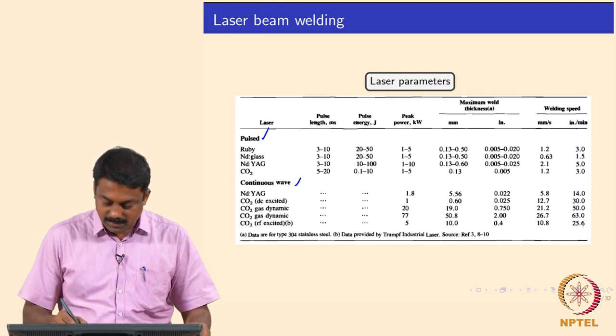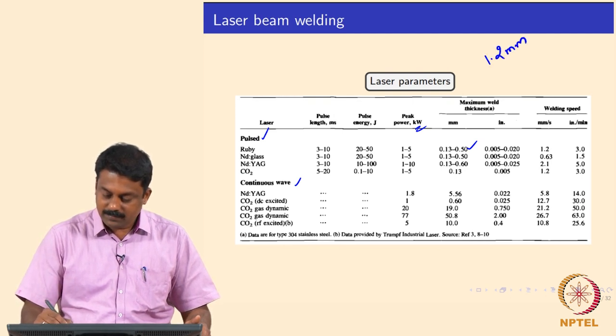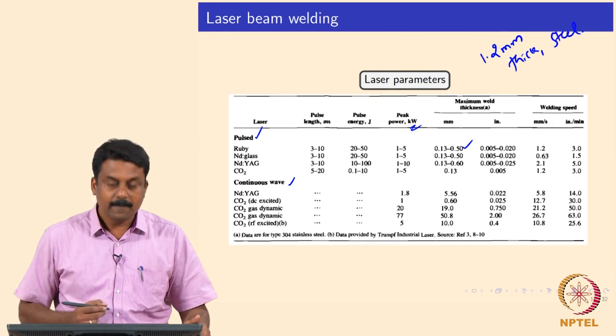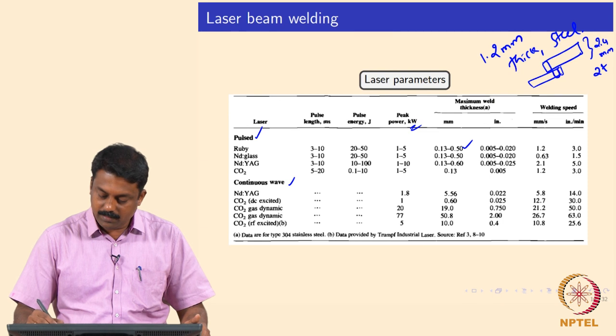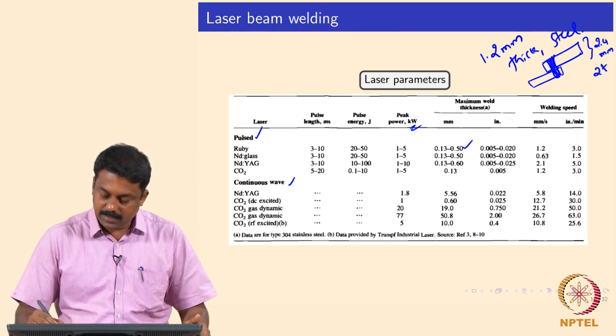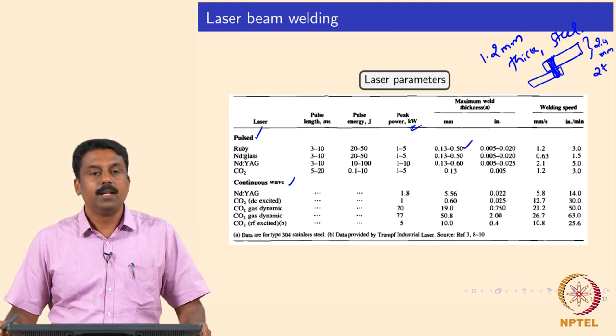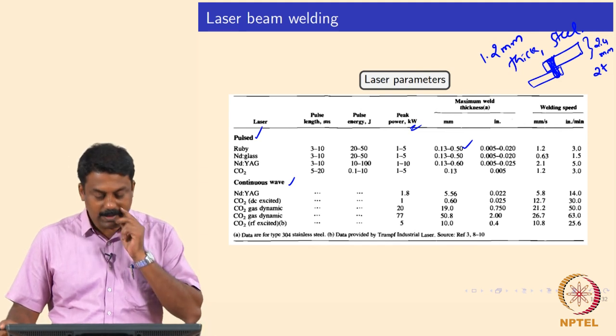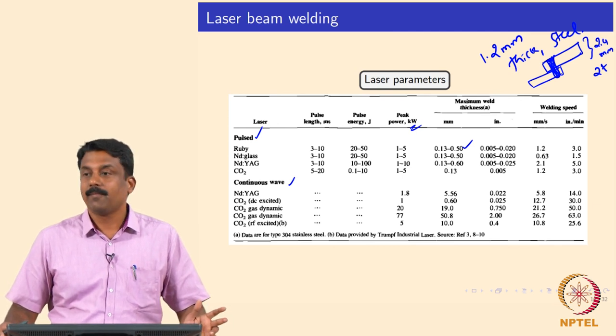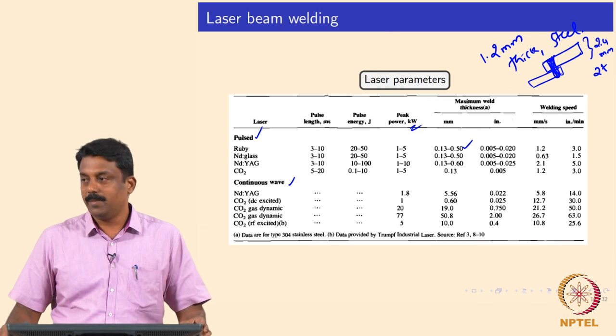For example, at 0.5 mm spot size, you can use 1 to 5 kilowatts. Generally, for 1.2 mm thick steel in an overlap configuration - which laser welding is generally done in - two layers put together will be 2.4 mm. If you want a full weld seam, 2 to 2.5 kilowatts should be sufficient for full penetration of 1.2 mm thick sheets overlapped to each other. For aluminium you need slightly higher power - the reason is the absorption is only about 10 percent for aluminium, whereas for steel it is about 20 to 25 percent.